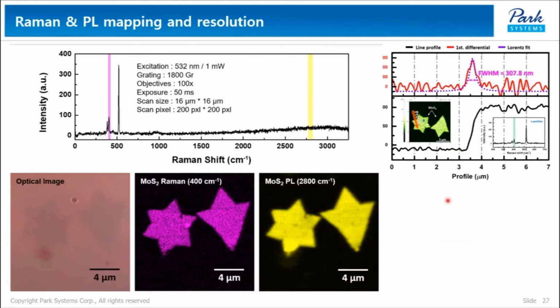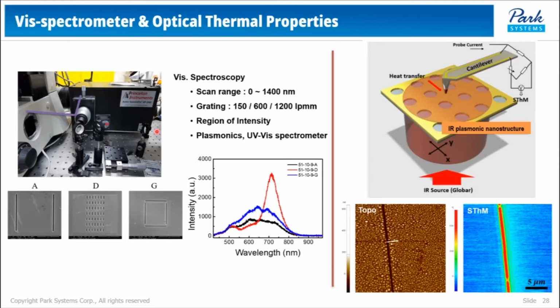These images show normal Raman resolution of around 300 nanometers, by the way, which is an excellent number. It also has the capability of visual spectroscopy. So these are different grating structures, and these different gratings can be distinguished by visual spectroscopy. And this data is measuring the IR-induced thermal signal on an IR plasmonic nanostructure.